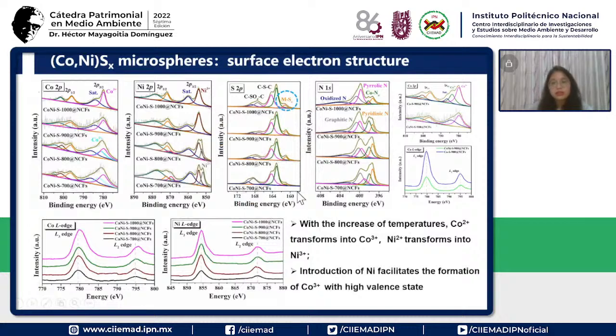For the surface electron structure, we also did a lot of work like XPS and soft synchrotron. After the analysis, we can see that with the increase of the temperature, at the beginning, at the low temperature, they show cobalt 2+ and also cobalt 3+. But when the temperature increased to 900 and 1000, it shows only cobalt 3+.